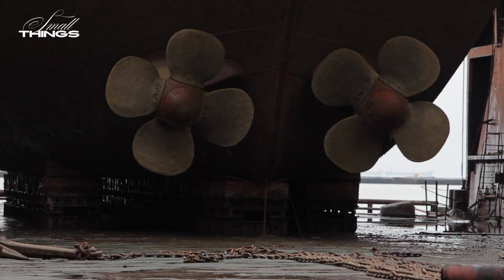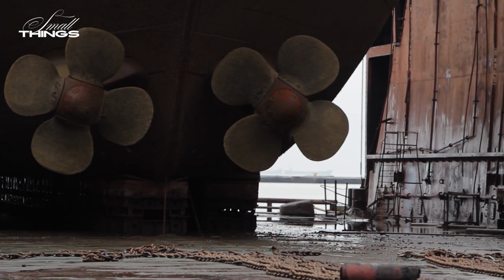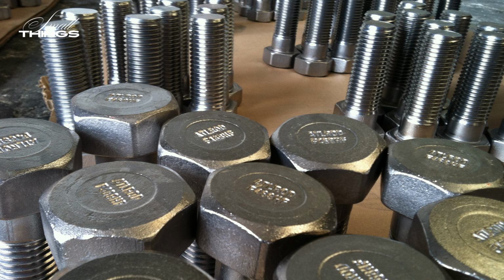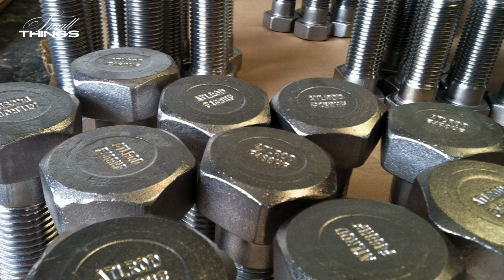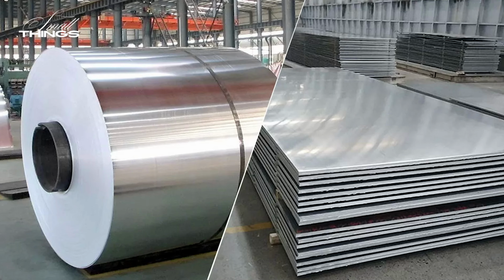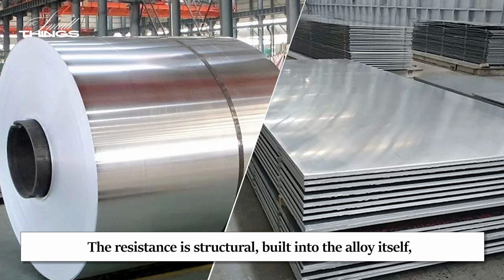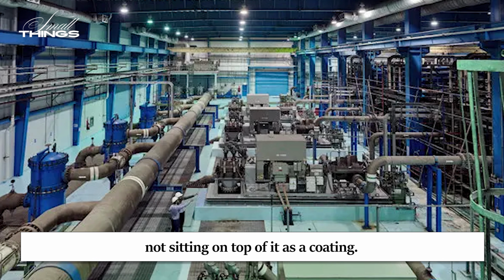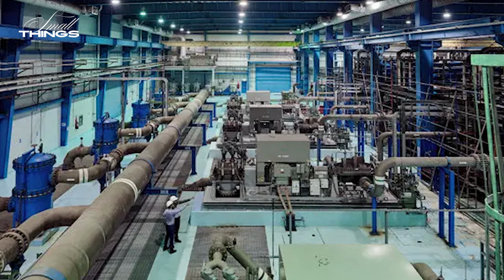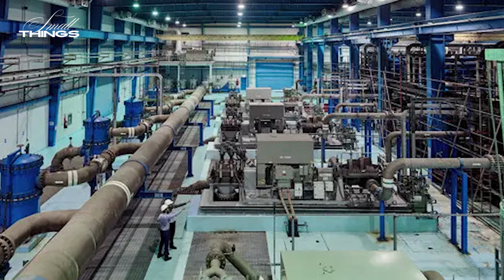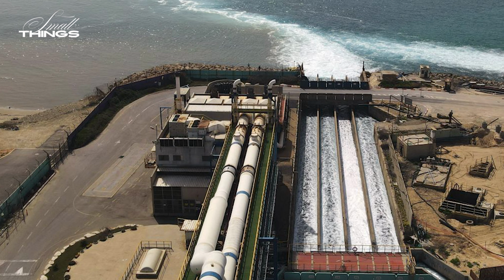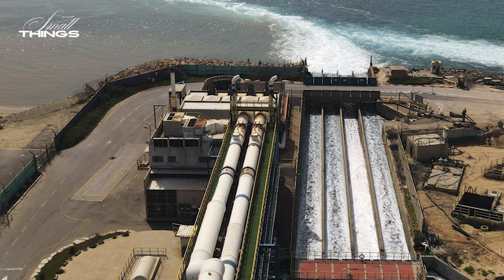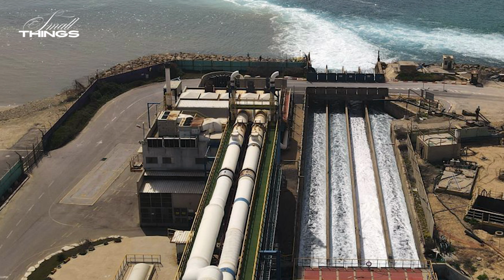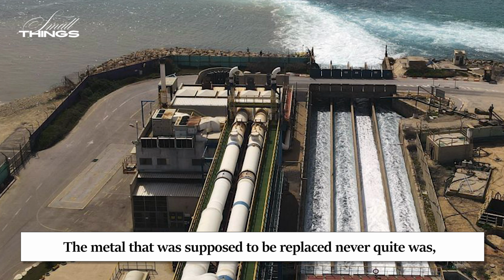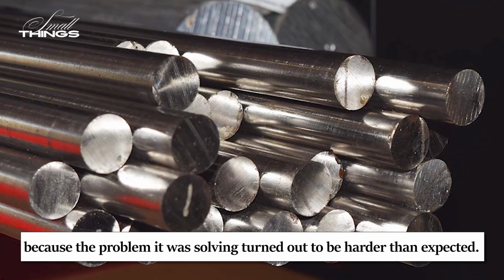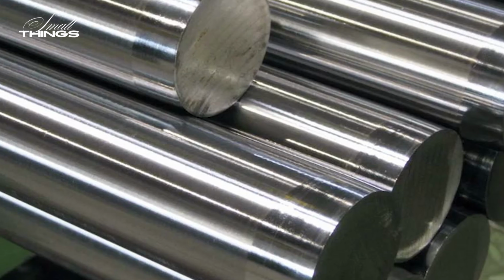Monel resists this mechanism because of what nickel and copper do together at the surface. Unlike the passive film of stainless steel, Monel's surface protection does not depend on a fragile oxide layer that chloride ions can penetrate. The resistance is structural, built into the alloy itself, not sitting on top of it as a coating. That distinction turns out to be the reason Monel is still specified for marine valves, propeller shafts, and seawater pumps more than a century after it was developed, in applications where stainless steel has been tried and found to fall short. The metal that was supposed to be replaced never quite was, because the problem it was solving turned out to be harder than expected.